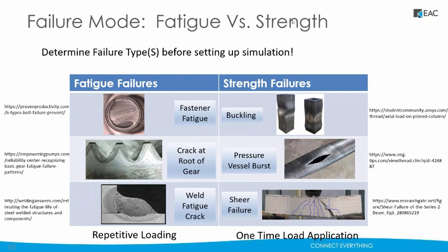Just driving home again the different types of failure modes. The picture's worth 1,000 words, I think, and so I kind of want to pass through these. For the strength failures here on the right, you have your buckling type failures, you have burst failures in components, and then you might have a full-on failure, such as shear or crushing or tensile failure. Now, on the left-hand side, most fastener failures are usually fatigue-induced, and cracking in small fillet radiuses is also generally a fatigue-induced phenomenon. And finally, most welds also fail due to fatigue cracking.